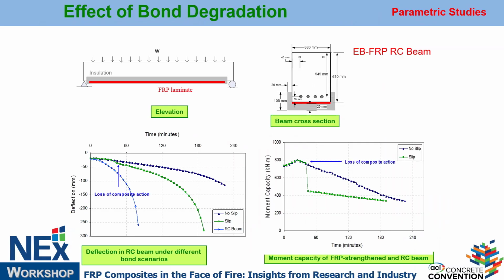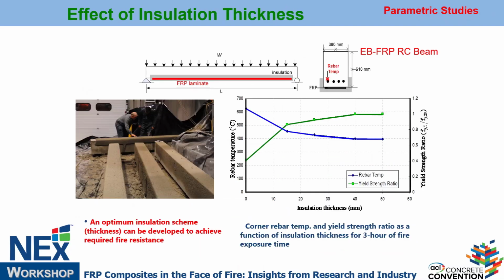Then, what about bond? Bond is the major issue. It has to be accounted for. This is the response of moment capacity, how it drops with time. If you don't account for constitutive relations for bond, then this is full slip, this is no slip, but it's somewhere in between. And that property depends on the type of the FRP, whether you're using GFRP, CFRP, right? That needs special constitutive relations. And how much thickness you need.